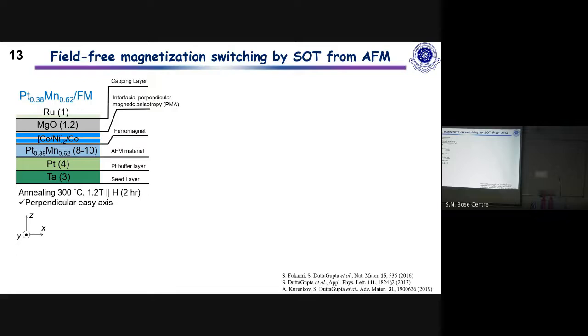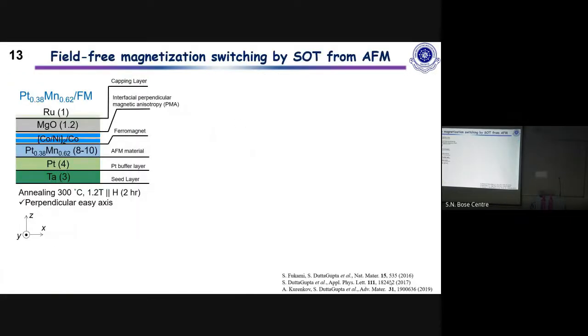So once we established that the antiferromagnet could be a source of spin Hall effect, then we wanted to go to the next question, whether it can be used to reverse the magnetization of an adjacent ferromagnet. Now, many of you can ask me that if you look at the slide, we have changed the ferromagnet. Previously, the ferromagnet was cobalt iron boron, and now it has suddenly become something different. It is because we were not able to get a perpendicular magnetic easy axis with cobalt iron boron for some reason. So we had to change the ferromagnet into a different one. With this ferromagnet, we were able to get a perpendicular magnetization. Even though we would like to have cobalt iron boron with a perpendicular magnetization in the system, it didn't work out for us.